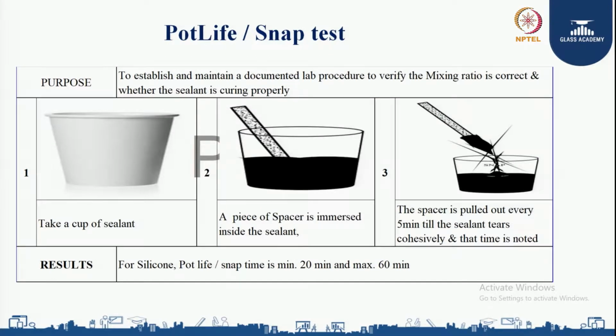Next test is the pot life or snap test. This test is performed to verify the mixing ratio is correct and whether the sealant is curing properly. The procedure is: first take a cup of sealant, then a piece of spacer is immersed inside the sealant. The spacer is pulled out every 5 minutes until the sealant tears cohesively, and the time is noted.